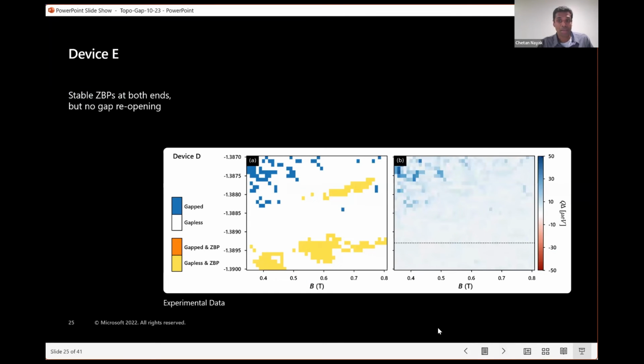We also saw devices that didn't have a topological phase, and we still do. There's some fraction of our devices that only have trivial phase. They fail the topological gap protocol. Here's an example of such a device. It had stable zero bias peaks at both ends, like these yellow regions, which are actually reasonably large. And then if you look at the phase diagram here in this blue-red color scheme, you can see it's all pretty trivial. There's just all sort of pale blue. There's no place where the gap reopens with a stable zero bias peak. So this is an example of what a quote-unquote boring phase diagram in a failed device looks like.